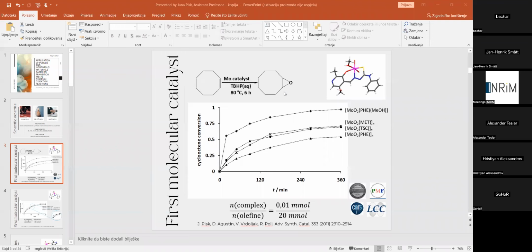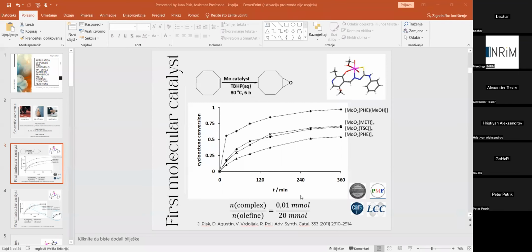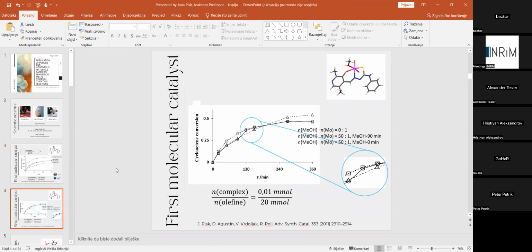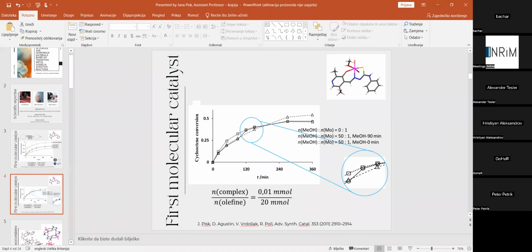In fact, these were the reactions where we worked on minimal catalyst loading. And when I say minimal, you can see the ratio of the complex and the olefin that we used. The first results that we obtained were quite impressive, because with this kind of complexes we got a very good catalytic conversion. So the cyclooctene conversion was quite high, and the selectivity towards the epoxide, which was the desired product, was also very good. We did more detailed research, and we successfully published those results, which I will not speak about in detail.